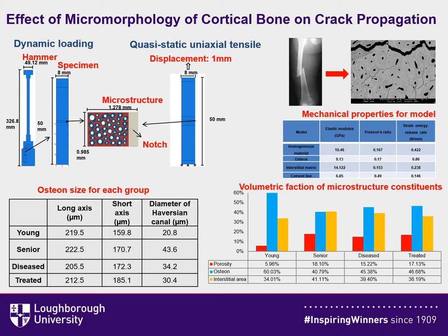The next step of our research was to look at the effect of different features on the fracture in human bones. And here we were considering four groups of patients: young, senior, diseased, and treated. At the first stage, we were looking at the microstructure and distribution of its main constituents. And even from these data, you can immediately see a significant difference, say, between the young and senior groups in terms of porosity. And people who are dealing with porous materials would immediately understand the disadvantage of the senior group in these terms. The fraction of osteons is significantly larger in young people than in the seniors. And there are some differences in both diseased materials and people who were treated with different medications.